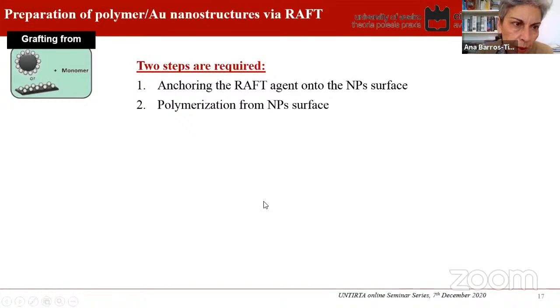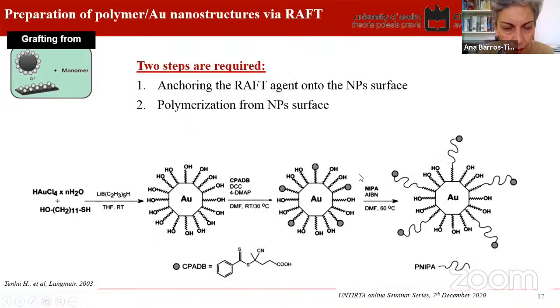The other approach that we had looked into was the grafting from. In this case, we have two steps. First, we have to anchor the RAFT agent onto the nanoparticle surface, and then the second step involves the polymerization from the nanoparticle surface. Again, we had seen in the literature that people had looked into this. So prepare the nanoparticles, and then promoted the anchoring of the chain transfer agent or the RAFT agent onto the surface of the nanoparticles, and from there grew the polymer chains.